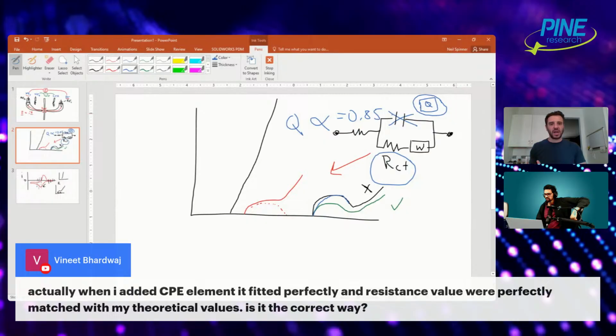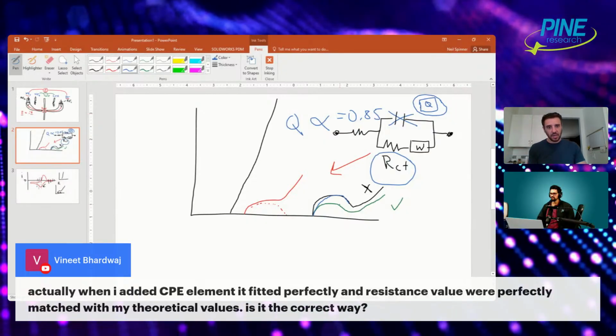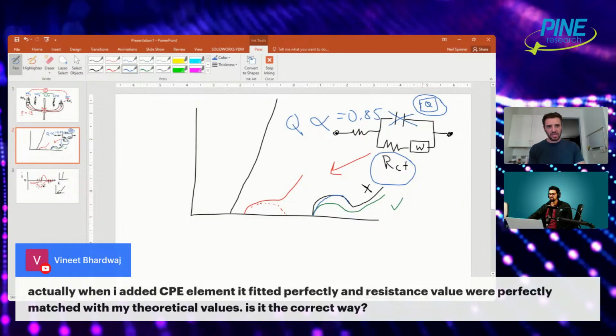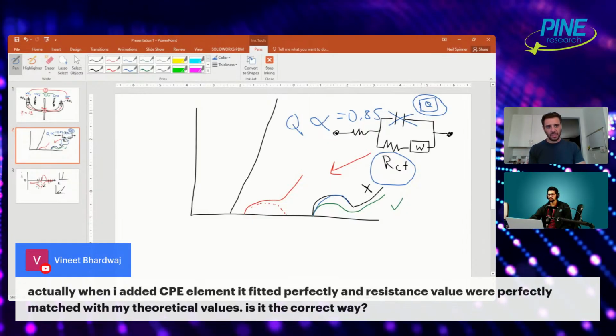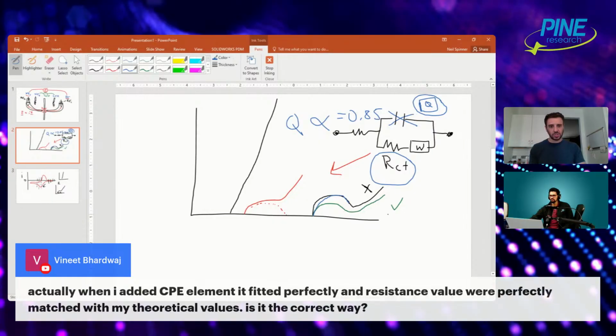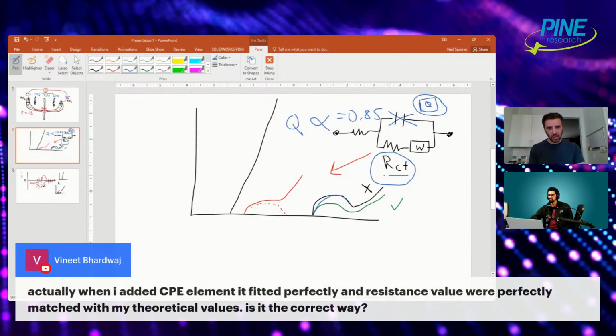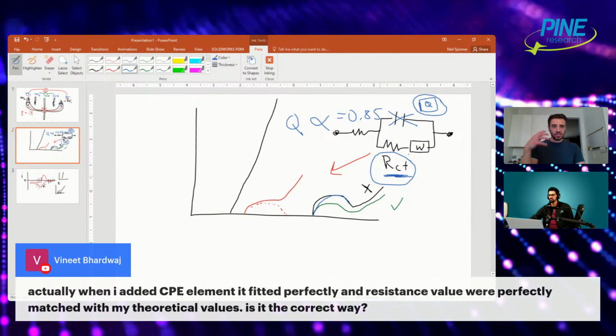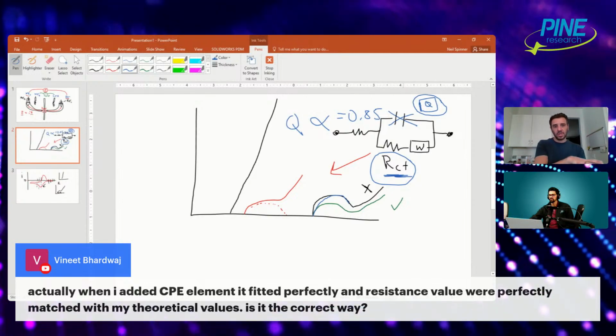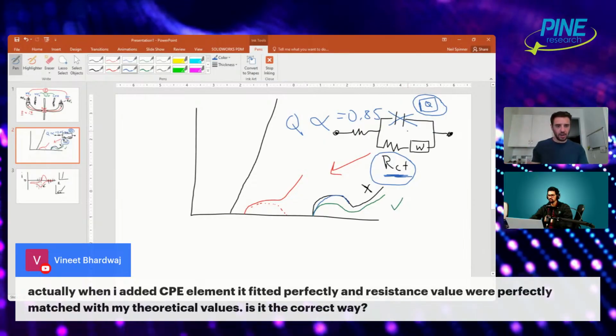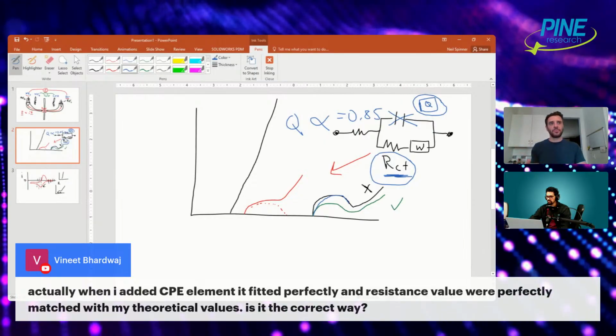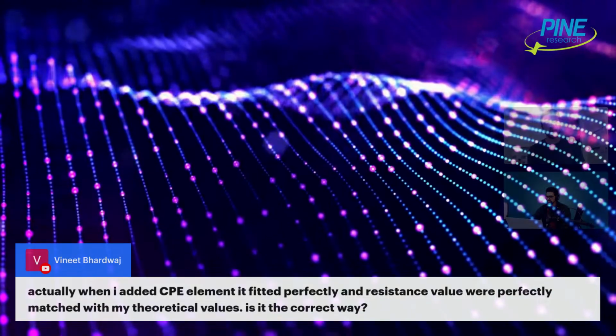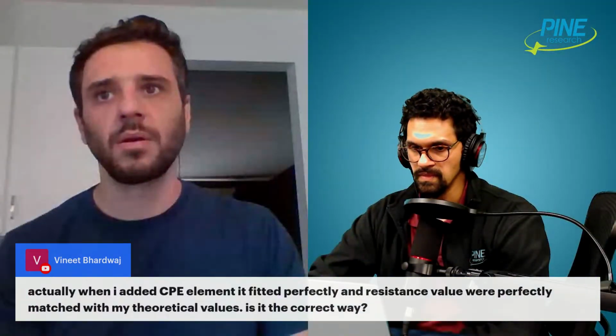So from that perspective, I think it does make sense, because using a CPE as an engineering tool to fit the capacitive data is useful so that you can fit the RCT, because that's what you're really after. And so you're fitting the other stuff whatever way possible to get at the information that you really care about, which is the charge transfer resistance. So from that perspective, I think that it is a reasonable thing to do. And frankly, most people do that in the literature. They fit CPEs most often, I would say.